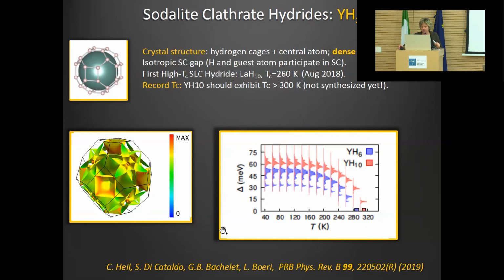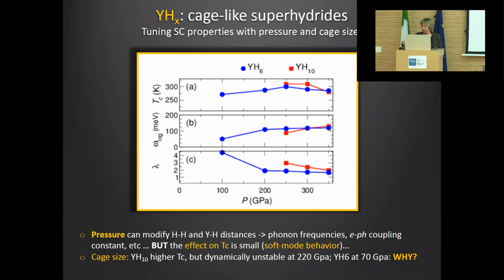Here what I show are the basic superconductivity calculations of the gap of two of these compounds, yttrium H10 and yttrium H6, as a function of temperature. From this you can see yttrium H6 has been synthesized, yttrium H10 has not been synthesized. For yttrium H10 one predicts a critical temperature larger than room temperature. One thing is the critical temperature, but one also has to check the stability. And here what we show are calculations as a function of pressure. As you see, these curves have a very different extension. The reason is that yttrium H10 has a high critical temperature, but is stable only at very high pressure, while yttrium H6 is stable up to lower pressure.